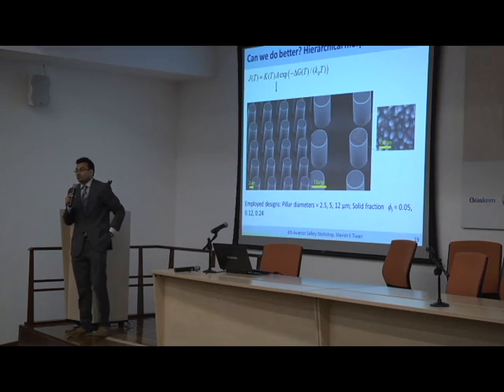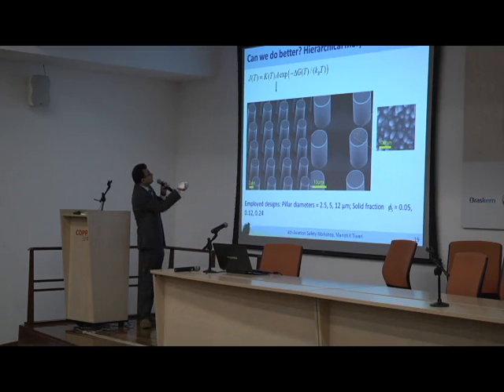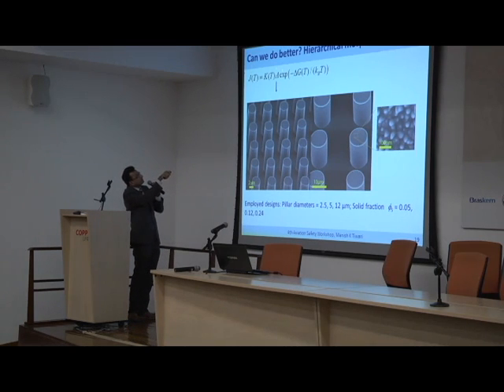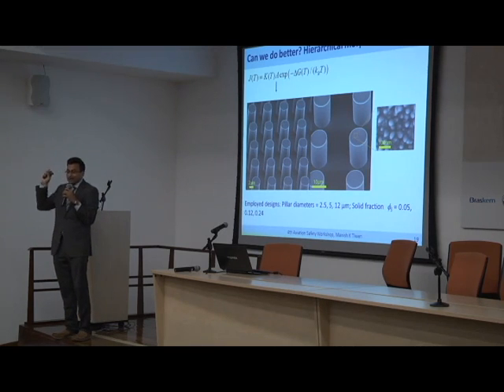Can we do better? So we have forgotten about superhydrophobic surface, and I'm going to try to bring it back now gradually. Okay, so let's see if we can make use of that. Can we do better? Well, turns out yes, we can do better. If we think in terms of nucleation rate, this is how the equation looks like, and up until this point I've tried to avoid equations as much as possible, but at this point I can't. So what we can do is look at this nucleation rate equation, which has surface area of contact between your liquid and the solid surface built into the equation. So if you minimize the contact area between liquid and the solid surface, you minimize the probability of icing. If my liquid droplet was sitting on air, I will have the least amount of possibility of nucleation, right?